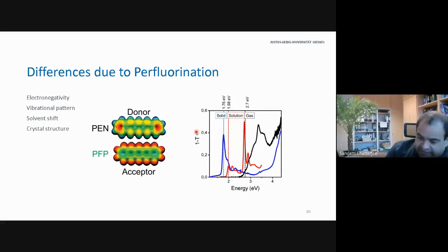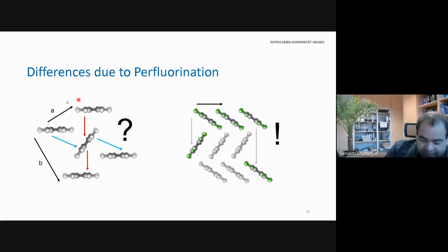Actually, pentacene is very difficult, and let me touch upon this slide very early on, because the stacking pattern of pentacene crystals shown here on the left is challenging, because the differences between the molecules are all about the same. If you calculate the coupling between the molecules, they're all the same. This system is very nice, but it also exists in very many different polymorphs and it's challenging. So we thought, let's look for something similar but easier, and we ended up with the perfluorinated species.